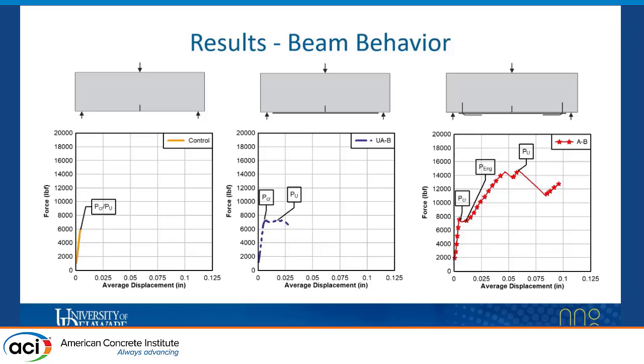Then when anchors are installed, again, you see the same behavior as you did for the past two beams. However, at the region of concrete cracking, rather than the initiation of debonding, you see a change in specimen stiffness, which is the indication of where the anchors engage up until ultimate capacity, and then the specimen fails.